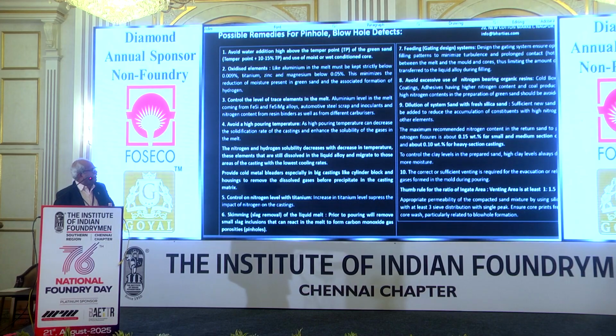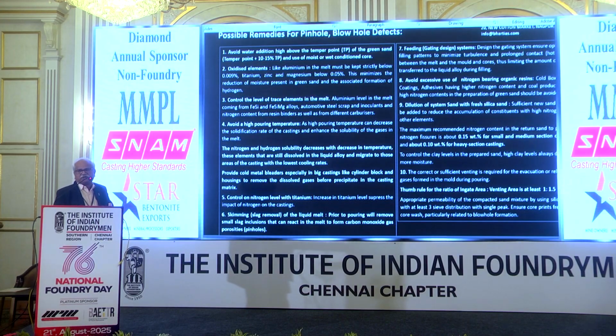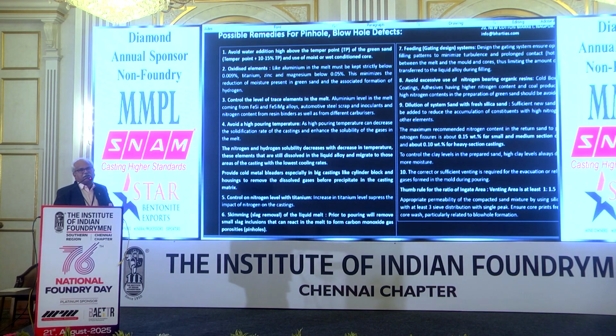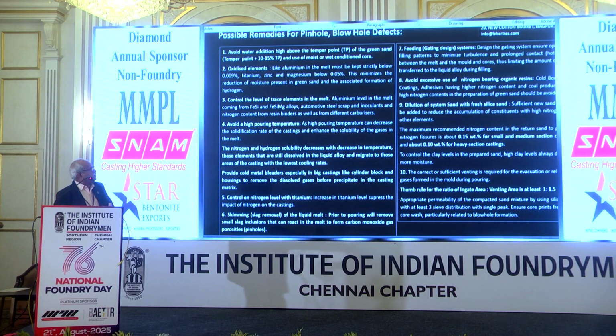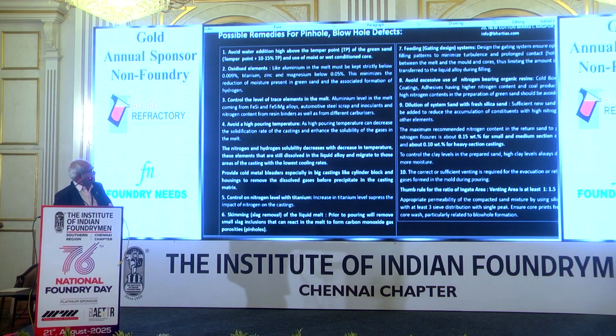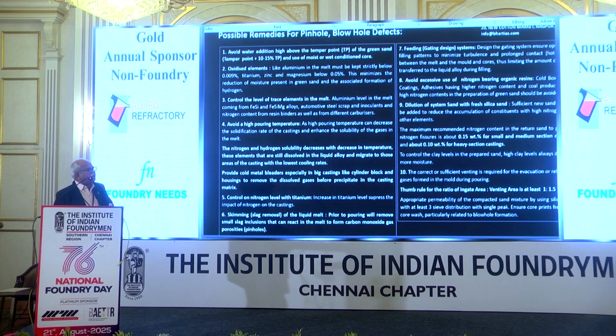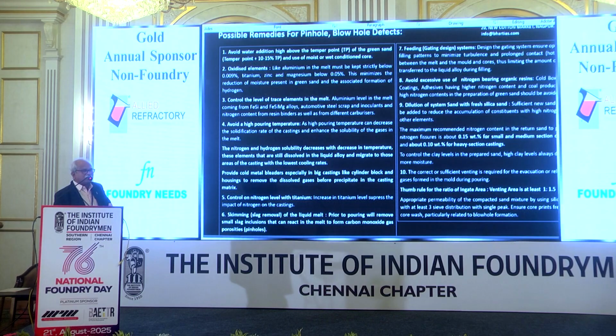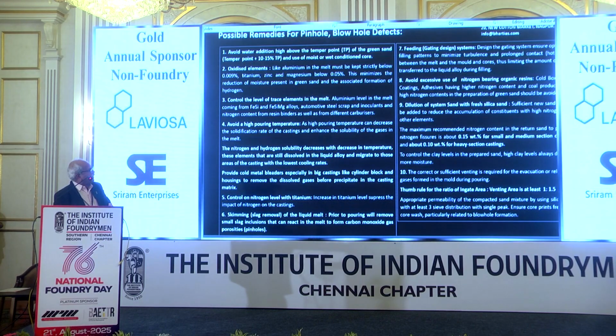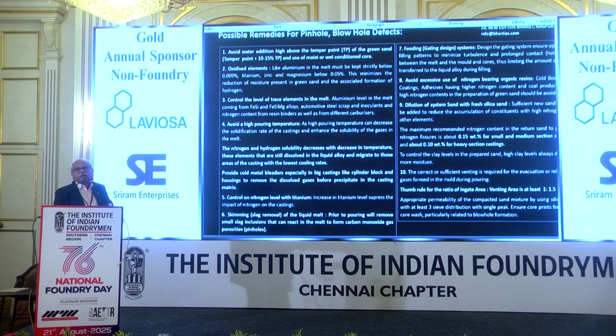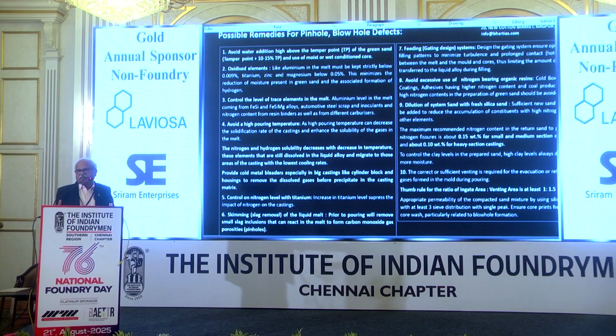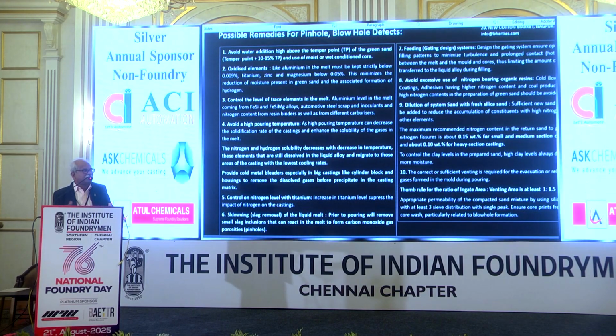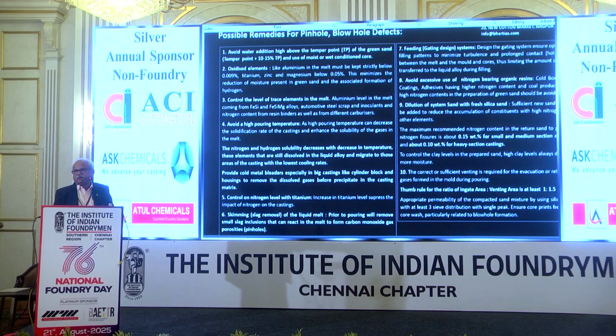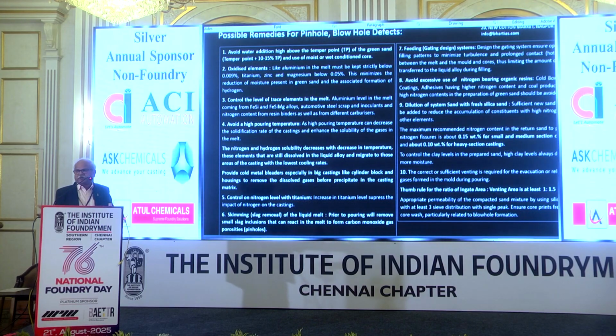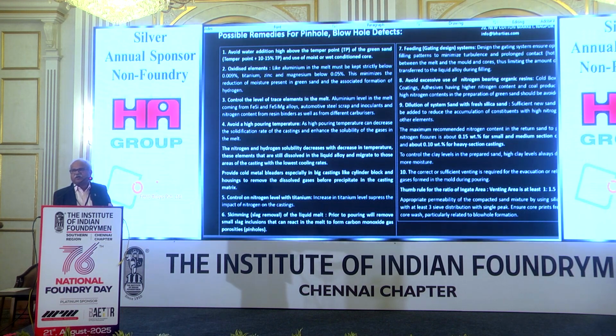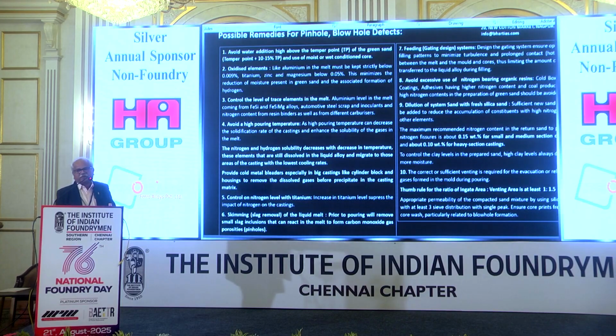Avoid excessive use of nitrogen-bearing organics. I already explained that nitrogen-bearing resins means cold box resins. These resins have a higher nitrogen percentage, and it generates the defects. The threshold limits are also given here. Some adhesives or coatings also release nitrogen gases, so dilute the system sand with fresh silica sand. When the excess level of these gases increases in the system sand, we need to add more fresh silica sand, increasing it up to 10 to 15% of LMT, liquid metal poured in the mold. That will dilute these gases.